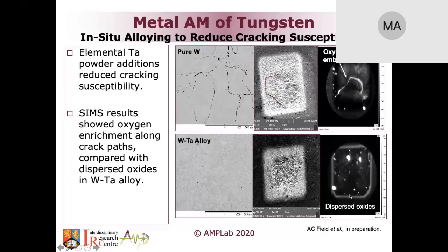So the key point is it did work. Tantalum acted in two ways. One of them is that it increased the solubility limit of oxygen in the matrix of the tungsten tantalum alloy. Second thing is that it acted as a getter, so it sucked up all the oxygen, creating a dense, crack-free alloy using that simple approach of just adding a small amount of tantalum while still keeping the alloy fusion compatible.